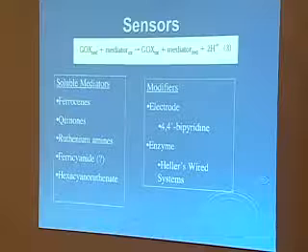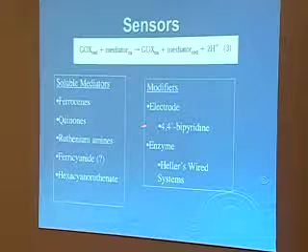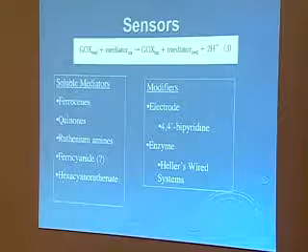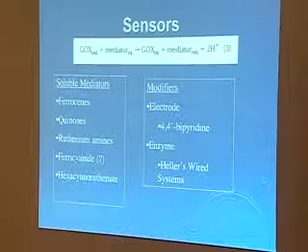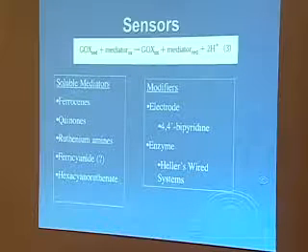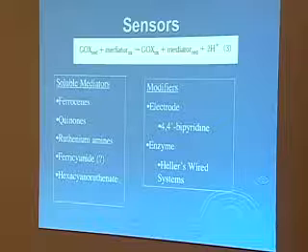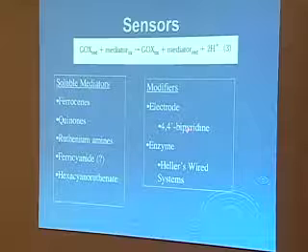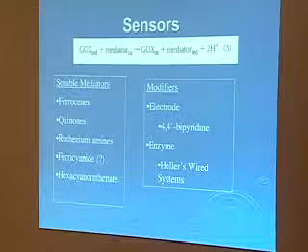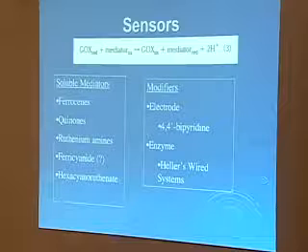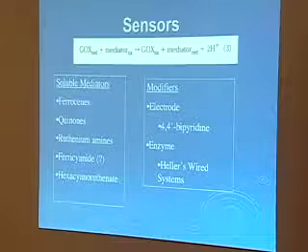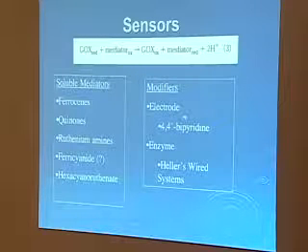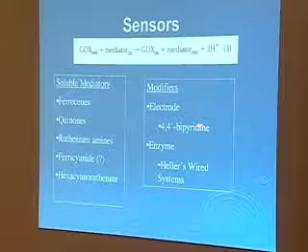There's other ways you can do this, it turns out, besides a soluble mediator. For example, if you take an electrode and just chemisorb onto it 4,4' bipyridine, then it acts apparently as an inner sphere sort of bridging ligand between the electrode and the active site in the glucose oxidase. And you get charge transfer in an electrode that has this on the surface, even though this is never oxidized or reduced in the process. So it just gives you a pathway, somehow sticking off the electrode and into the active site. And how that works is really unclear. There may also be an effect due to some denaturization of the protein or something like that. But this works. It's never been totally understood why that works.